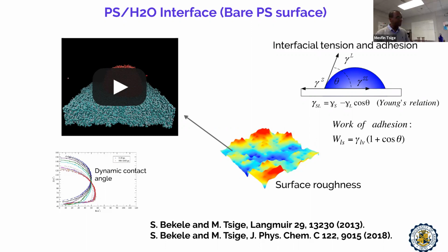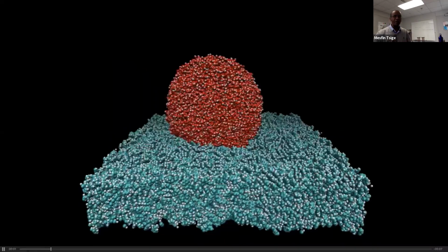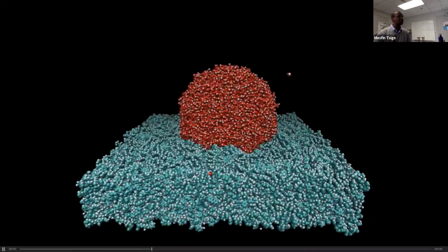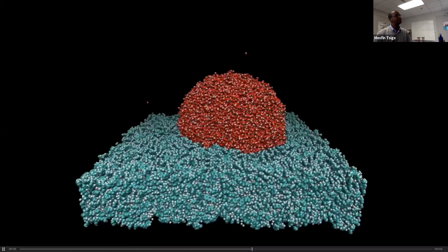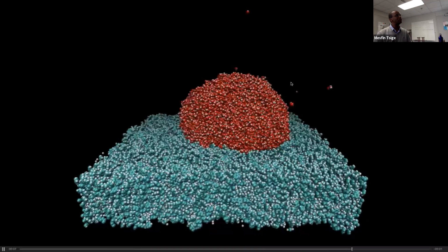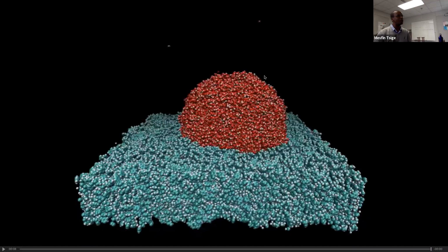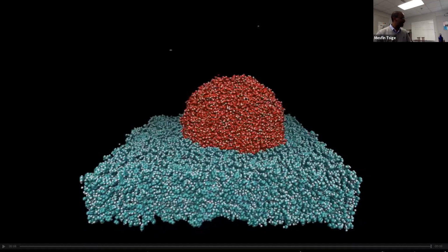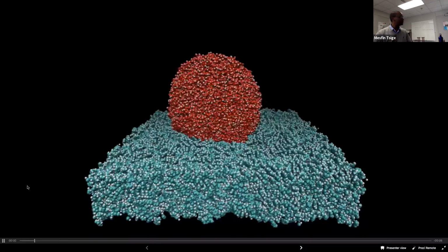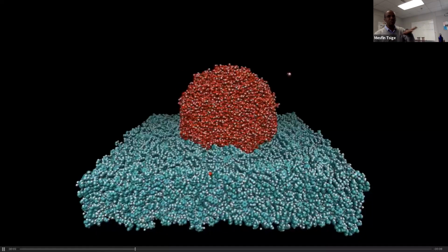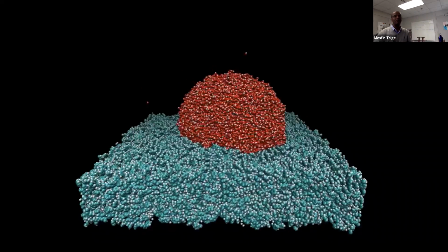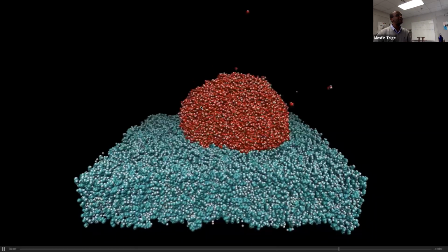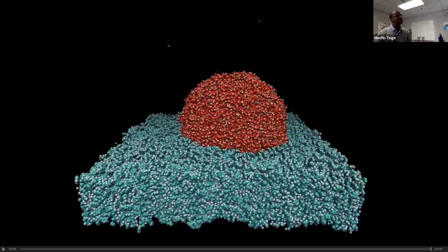Once we do that, we put our water droplet on the surface. So this is our polystyrene film. This is a water droplet. Each of the water molecules, some of them are evaporating, as you see. And because it is a rough surface, you initially see that when it bounces, it rolls off a little bit because of the roughness of the surface. And finally, it settles down to a contact angle of about 95 or higher.